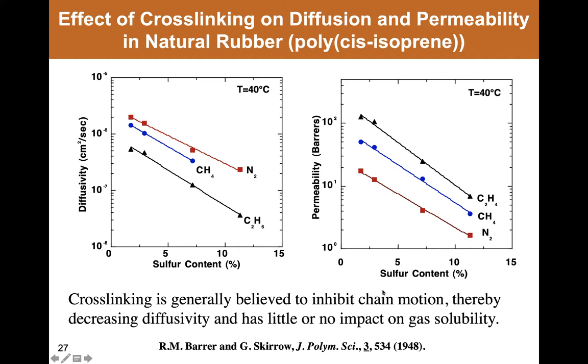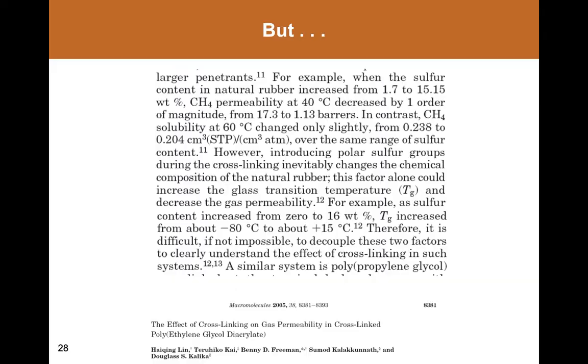The general discussion in a lot of the literature is that cross-linking decreases penetrant diffusion and transport phenomena by inhibiting chain motion and decreasing diffusivity. And in the case of natural rubber, that in fact is the case, but it's not always the case. And this is something that I want you to be aware of, particularly as you work on things like hydrogels and materials where the cross-links are rather far apart from one another.